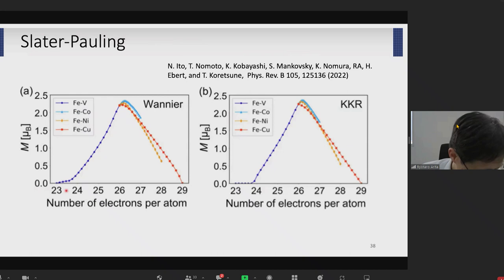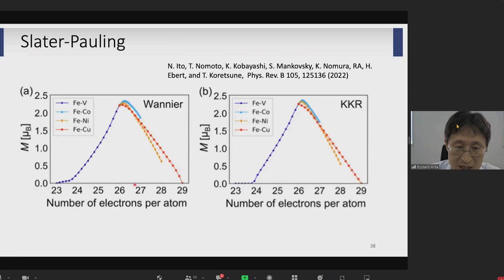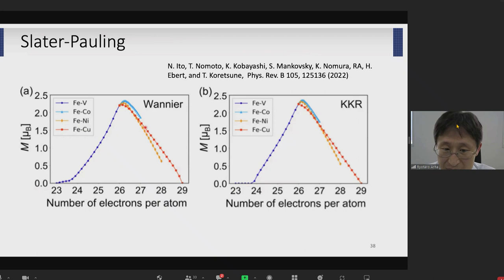This is a comparison between the Wannier-based CPA and KKR-CPA. Comparing pure copper and pure iron, and an alloy system of iron 0.6 copper 0.4, the results of KKR-CPA and Wannier90-CPA are basically the same. With this method, we can also obtain the so-called Slater-Pauling curve — the size of magnetic moment calculated as a function of the number of electrons per atom, starting with iron and considering alloys with vanadium, cobalt, nickel — and obtain the same result as KKR-CPA.